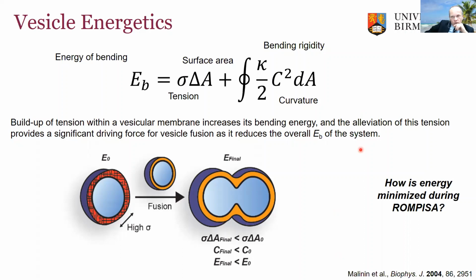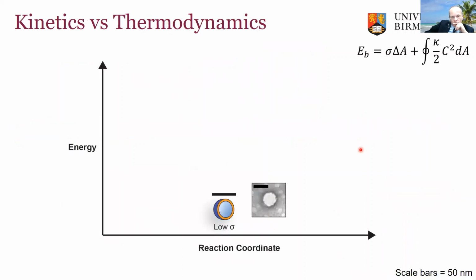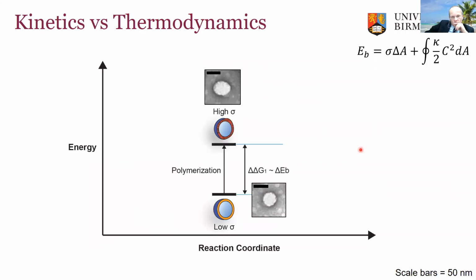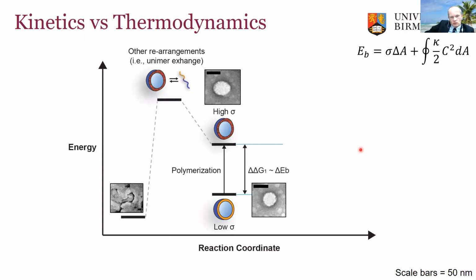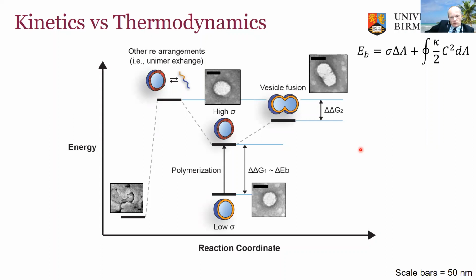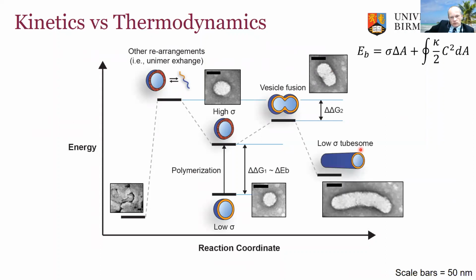So how might energy be minimized during our ROMPISA? If we start with a very low tension and with our initial polymersome, as we polymerize, that tension starts to build within that membrane. So we start to reach our higher tension system. If the polymerization is rather slow, you could imagine how you would then get rearrangements such as unimer exchange that would then lead to a loss of construct and reduction in energy. The other way to relieve the tension is vesicle fusion, where we get high energy for vesicle fusion, but then a reduction in energy as we form these low tension tubesomes and the worm-like structures that we've seen in our system.